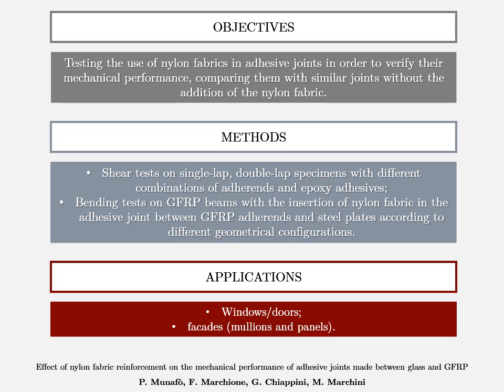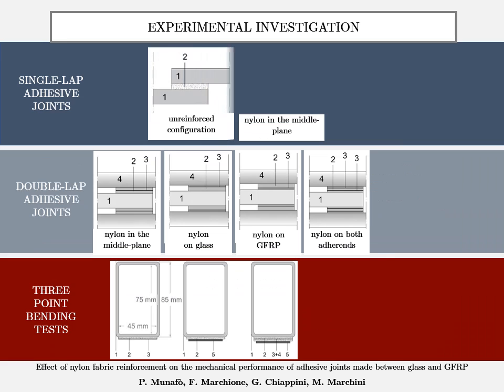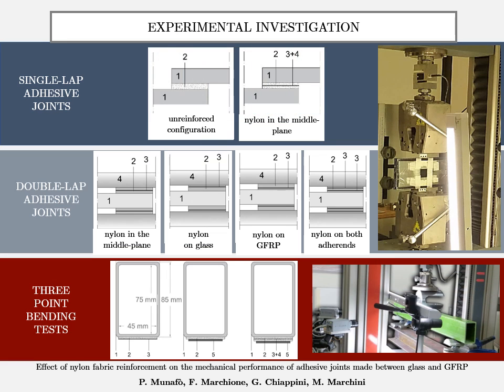The application area of the present study is the building industry, especially for innovative building elements such as windows, doors, and curtain walls. For the experimental campaign, a nylon 6 fabric was used. After identifying the appropriate material to increase the stiffness of the joints, experimental mechanical tests were performed after curing under laboratory conditions to test the adhesive joints assembled with epoxy resin.